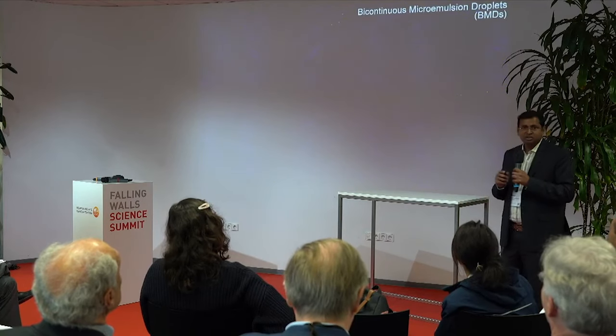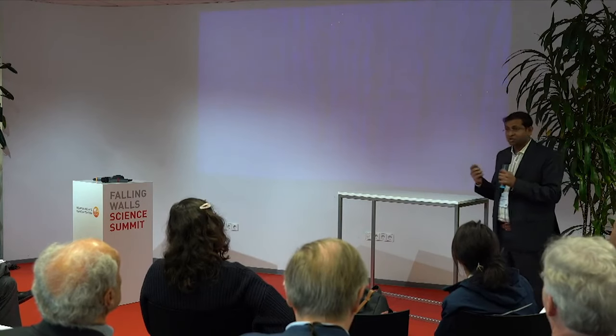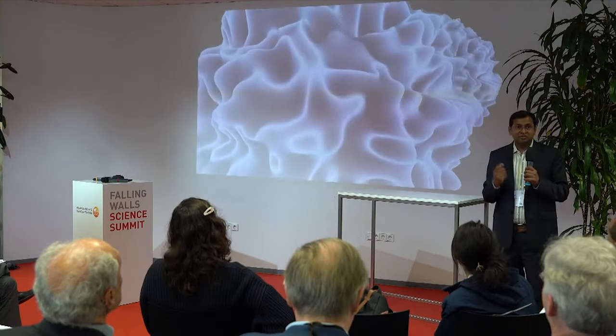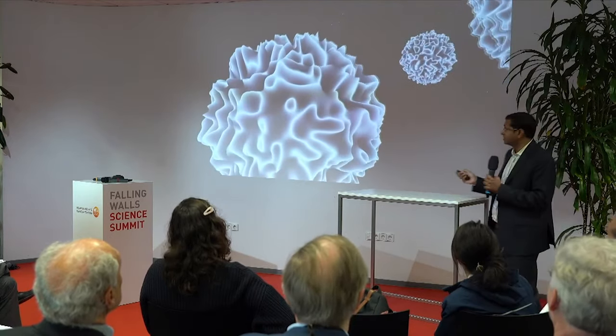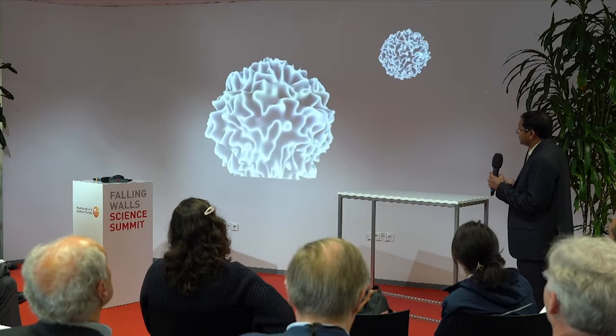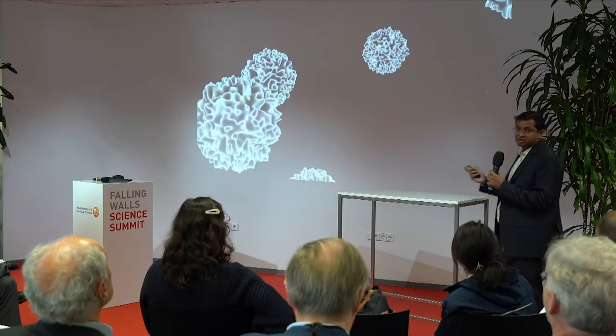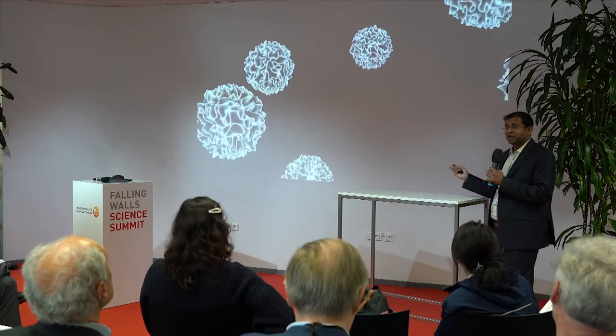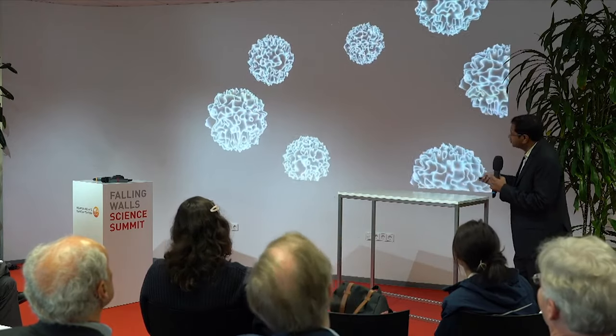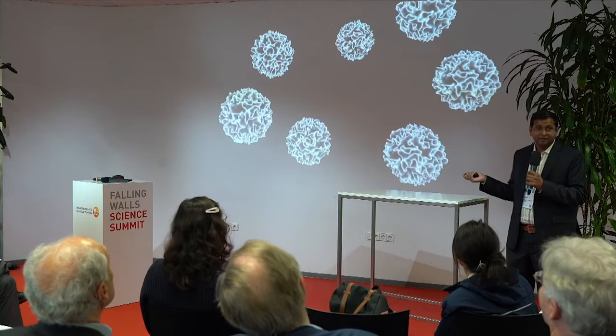But we also observe that these are not floating flat in the system, but they're in the form of a droplet, a micro-emulsion droplet. And these droplets then became a template to synthesize a different kind of nanomaterial. So this is a spherical droplet made up of xylene, water, and some surfactant molecule. These are not nanoparticles, but they're nano insides. And then in the channels, you can grow different materials, in this case, silica.